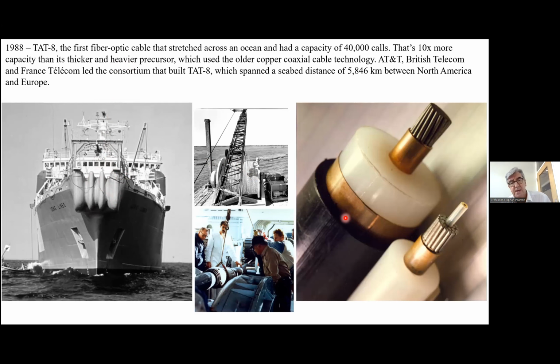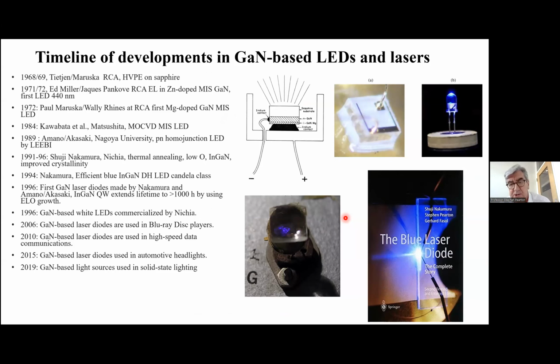Now, the next material that was commercialized was gallium nitride, initially as blue LEDs. And people were looking for blue and green LEDs to complement the existing red and amber devices that were already there from gallium arsenide and gallium phosphide. And key contributions were made by Amano and Akasaki at Nagoya, and Shuji Nakamura, at that time at Nichia, now at UC Santa Barbara. They made the first blue LEDs, and then Nakamura made the first blue laser diodes, and those technologies eventually led to white LEDs for solid-state lighting and laser diodes for high-density information storage.